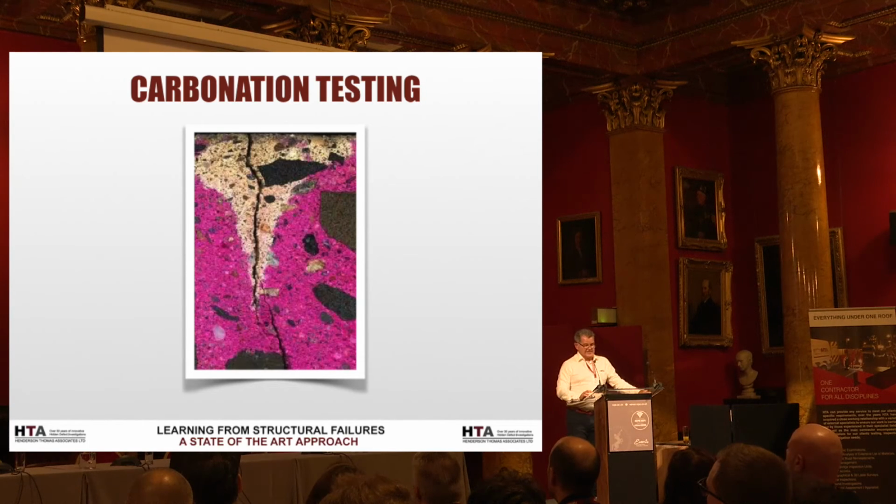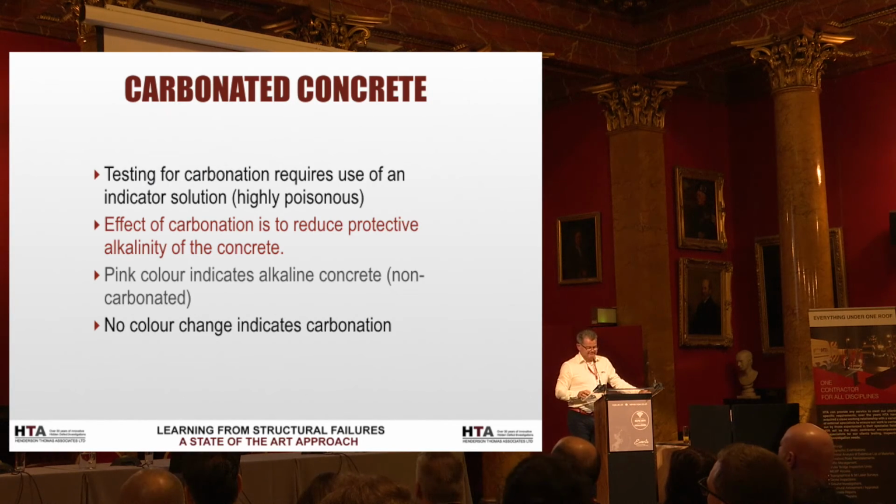We use an indicator solution called phenolphthalein. It's pretty horrible stuff. It's probably one of the worst things we take out on site. As I said, the pink color indicates non-carbonated concrete, i.e. it's as it should have been. What I would say is if any of you are near any of my guys who are using this, make sure you keep well away from them, or certainly upwind, because phenolphthalein in very, very dilute forms is used as a laxative. So you don't want to get a face full of it.